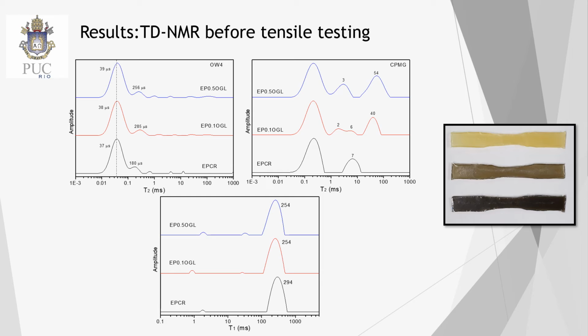present. The results of a longitudinal relaxation are also shown in this figure. This relaxation is sensitive to morphological change for spin diffusion paths of the order of 20 nanometers, while the transverse relaxation detects fluctuation in smaller segments.